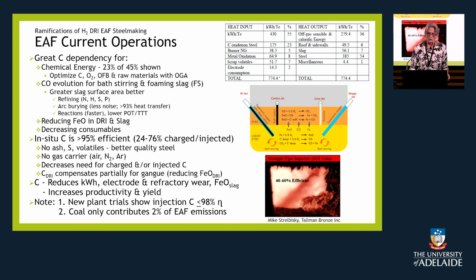It reduces the FeO in not only the DRI that's being fed in, but also the slag. And you can see that it will also decrease the consumables and the cost of making steel. The in-situ carbon that you find in the OBMs is much more efficient, 95+%. When you've got the injection or charged carbon, you're only getting between 24 and 76% of efficiency most of the time from those being added.